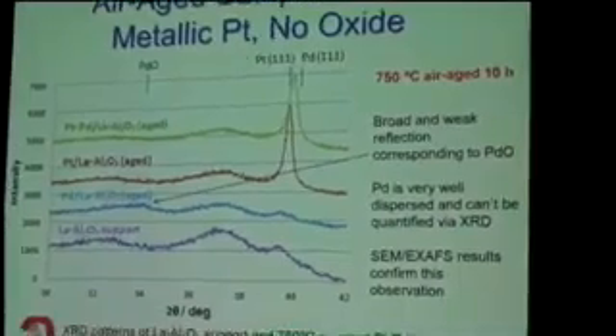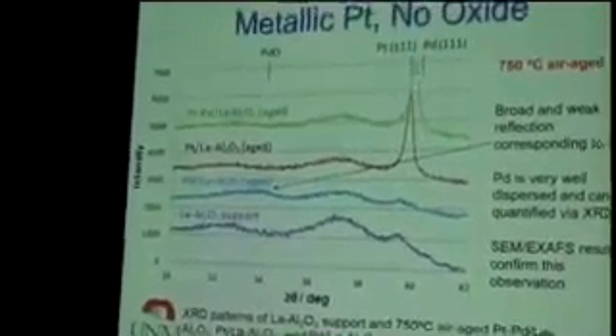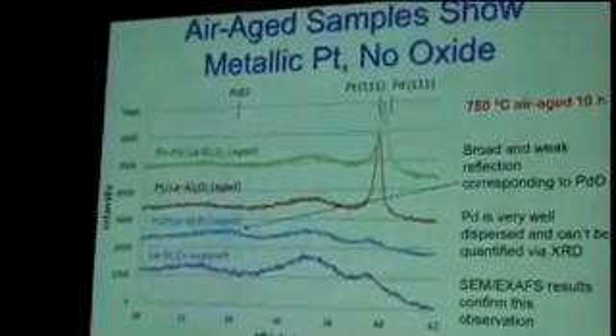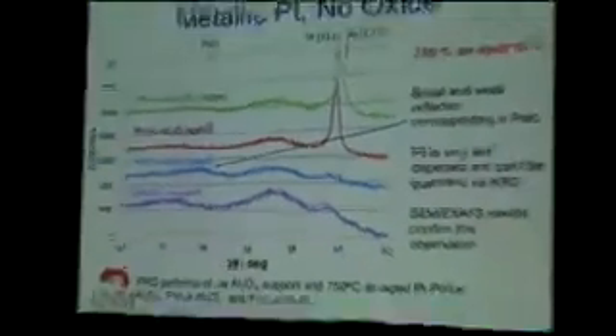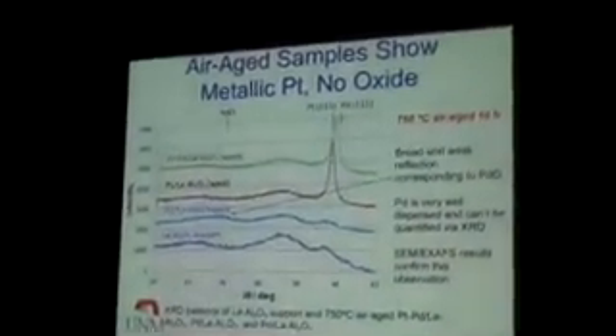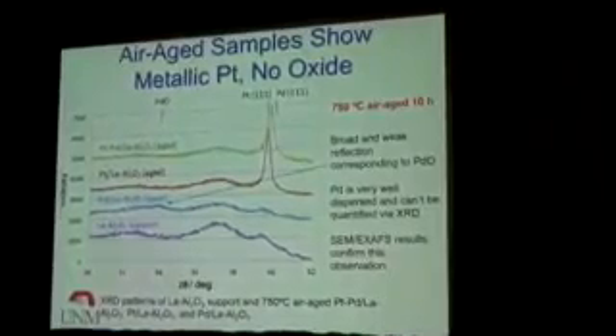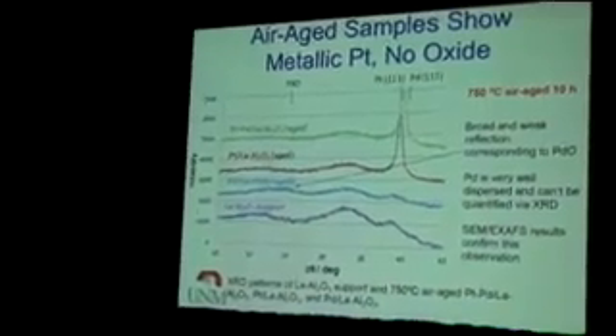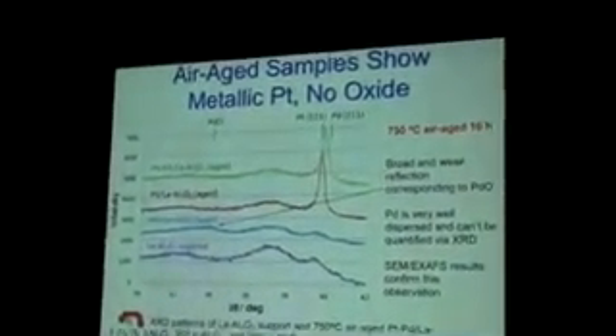If you use the palladium catalyst, you see nothing, because the palladium just remains well dispersed at this temperature. If you look at the bimetallic, it also shows a peak, and it's somewhere between the lattice constants of palladium and platinum. So this shows that indeed, if you have the platinum and palladium, and heat them in air, both the platinum and the palladium now are becoming metallic. Whereas by itself, the palladium is not metallic, and it's an oxide. You can barely see it here, it's in the mass. So the message is, there's not a thermodynamically stable phase of palladium oxide. But in the presence of platinum, it is actually metallic and bimetallic. And that's the key to this catalyst.